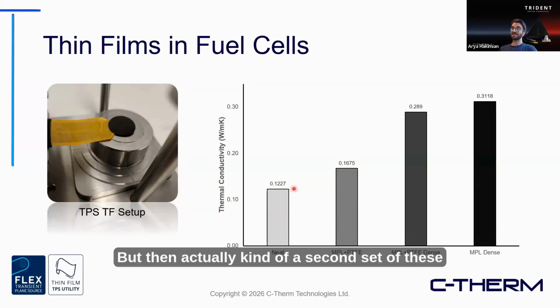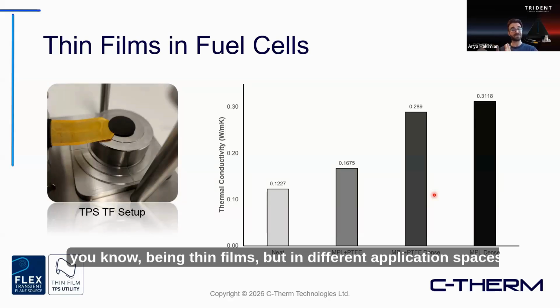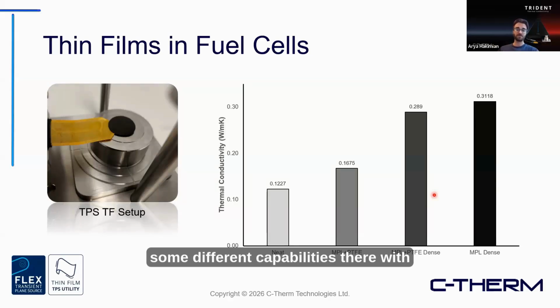But then there was a second set of these materials where it was densified, and we were seeing whether that significantly impacts the performance of the material. And as we can see, and as you may expect, the more densified the material is, the better the heat transfer networks will be, with an overall resulting increase in thermal conductivity. That being said, these different sample types, being thin films but in different application spaces, show some different capabilities with our thin films on TPS.